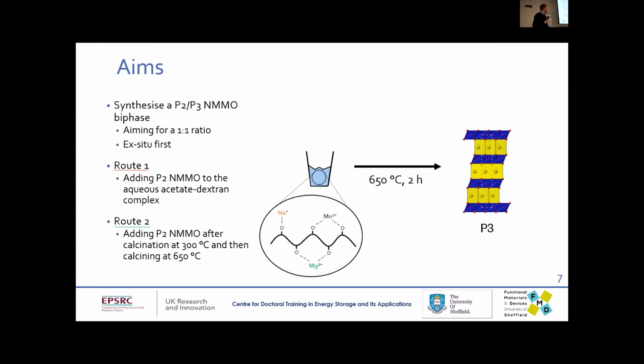So this is the original, this is how I would make a P3 cathode. This is the acetate dextran solution. This is the dextran molecule, and these are the ions coordinated to it. You dissolve it in water, dry it down, calcine at 650 degrees, and you get P3. What I'm going to do is at some point during this synthesis route, add a pre-made P2 powder and hopefully get the P3 to grow around it, so that they are in contact with each other.